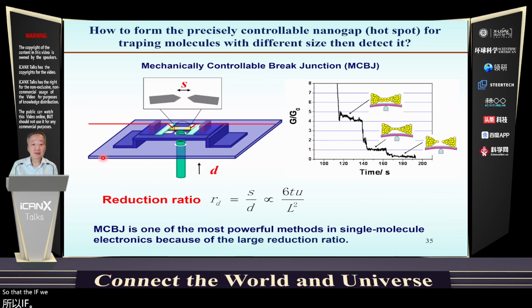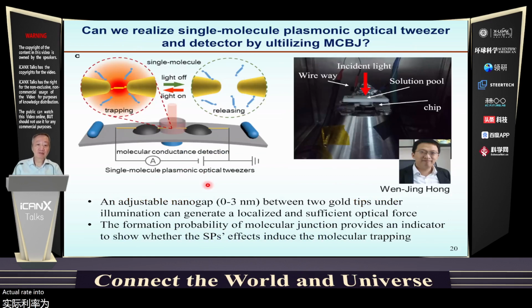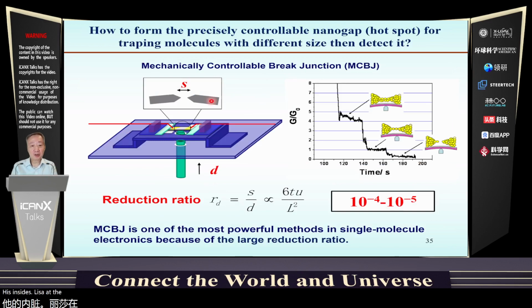So if we have a very thin silicon wafer, or another material that can bend, we can make this gap bigger and smaller by moving this actuator up along this direction. With this reduction ratio, the adjustable gap can reach about an angstrom or even sub-angstrom. Because as you can see here, if we move up by 1 micrometer, because of this reduction ratio, we can reach 1 angstrom easily.